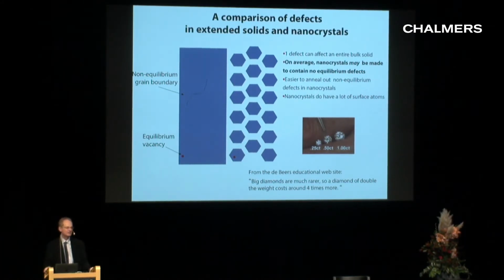Why is that? Well, because if there is a defect in the diamond, it won't look right. And you want that defect to go away over time. If the crystal starts to grow and there's a mistake in it, you want that mistake to slowly leave, and that takes geological time because the diamond is big. And so that's why the bigger the diamond and the more perfect you want it, the longer it takes for it to anneal out. It turns out that what we're studying now takes that problem and turns it upside down.